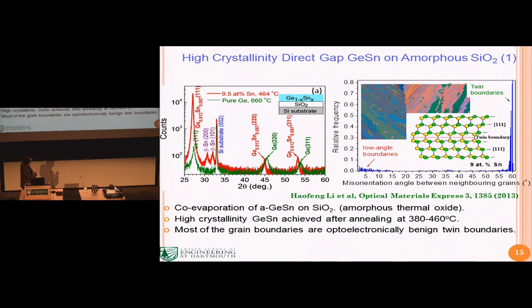We also have a small amount of low-angle boundaries. These places lead to tin segregation. As we'll show you later, if you control the growth more precisely, you can get rid of these small-angle grain boundaries, and you can get even higher tin composition into the material.